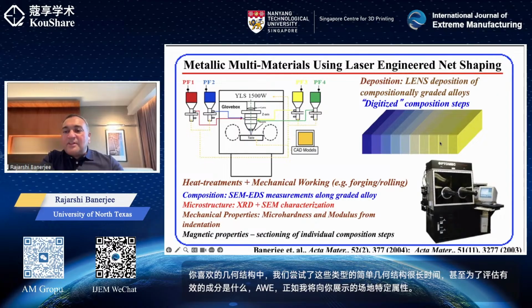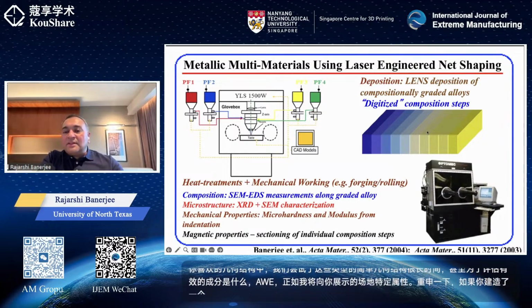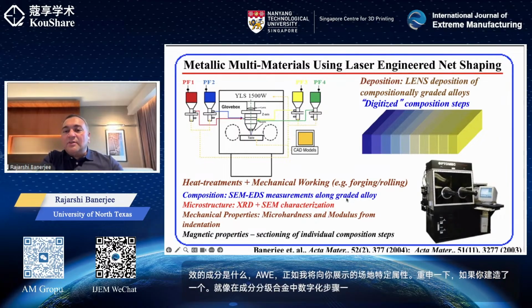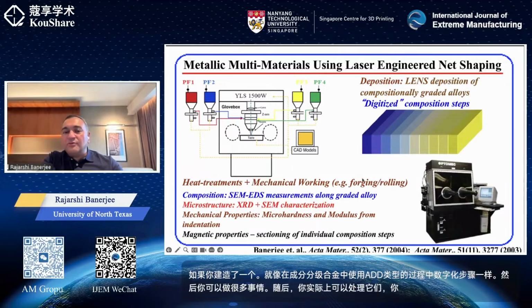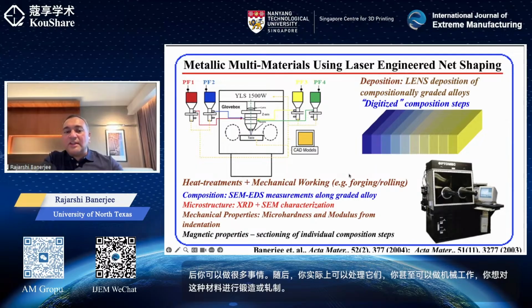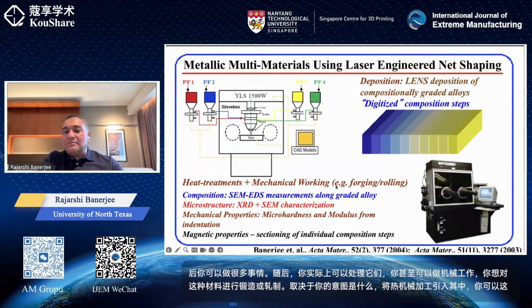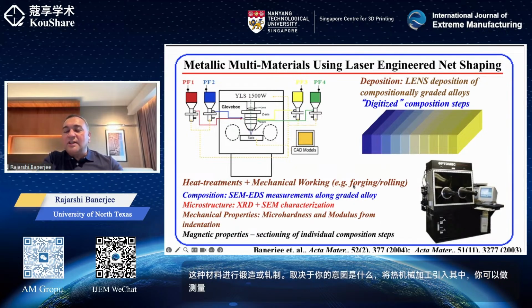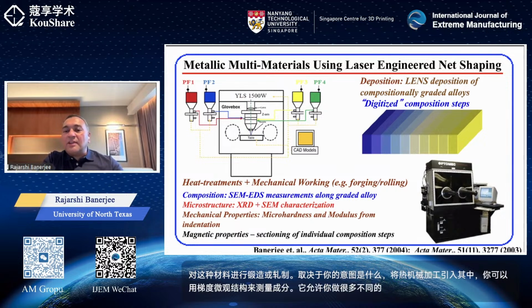like digitized steps in a compositionally graded alloys using a DED type of process, you can then do a lot of things subsequently. You can actually heat treat them. You can do even mechanical working if you want on this material, like forging or rolling, depending on what your intention is to, if you introduce thermomechanical processing into it. You can do the measurements of composition along the gradient, microstructure. It allows you a lot of different things to do in a single small range of a build. But you can even get mechanical properties like microhardness and modulus and so on.